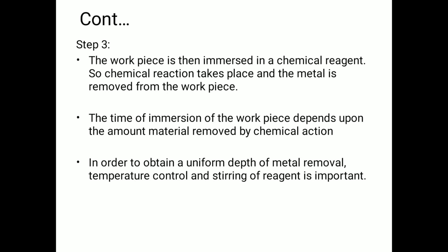After covering with the maskant material, the workpiece is then immersed in a chemical reagent. So a chemical reaction takes place and the metal is removed from the workpiece surface. The time of immersion of the workpiece depends upon how much material we want to remove from the workpiece. In order to obtain a uniform depth of metal removal, the temperature control and stirring of the reagent is important. So a stirrer is used.